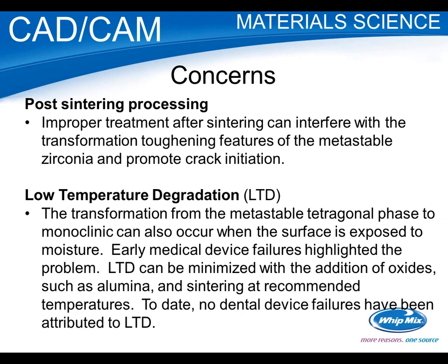The other is an issue called low temperature degradation. And when I showed those pictures of the hip components earlier, that was a big issue. I think it was in the early 80s where they had a number of failures after they were implanted in people.